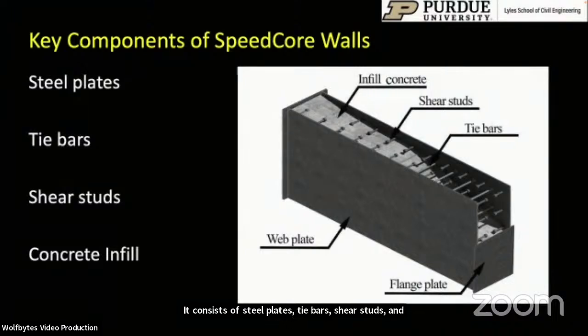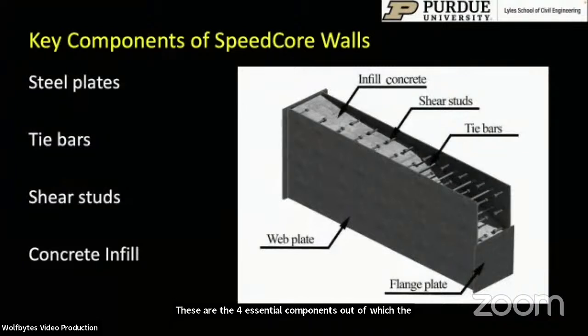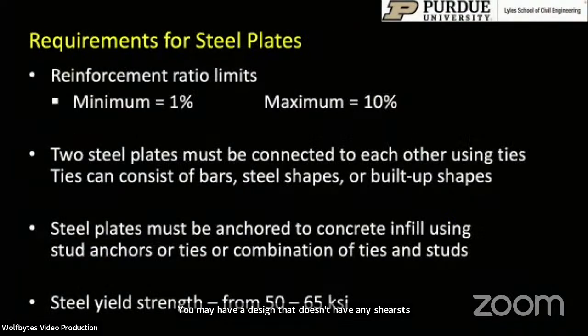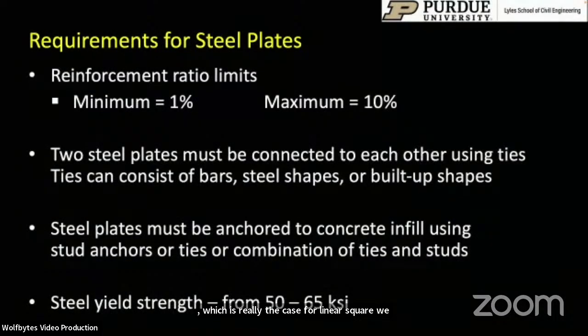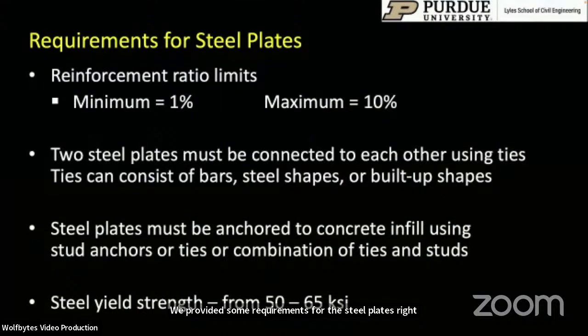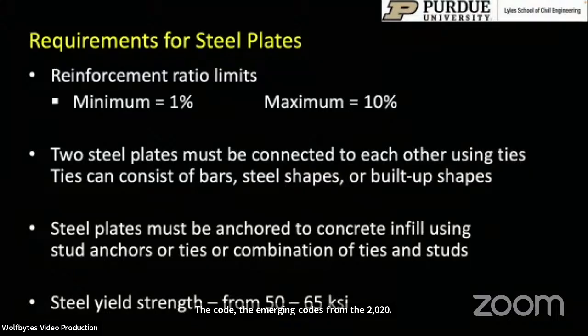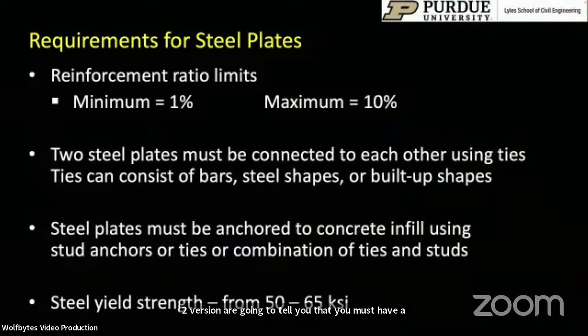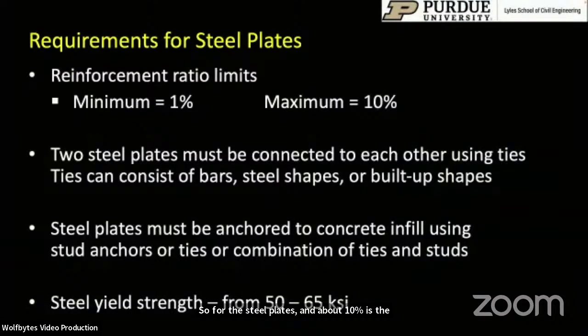These are the 4 essential components, out of which the shear studs are actually optional. You may have a design that doesn't have any shear studs, which is really the case for Rainier Square. We provided some requirements for the steel plates. Right now, the emerging codes from the 2022 version are going to tell you that you must have a minimum reinforcement ratio of about 1% for the steel plates, and about 10% is the maximum reinforcement ratio that is permitted.